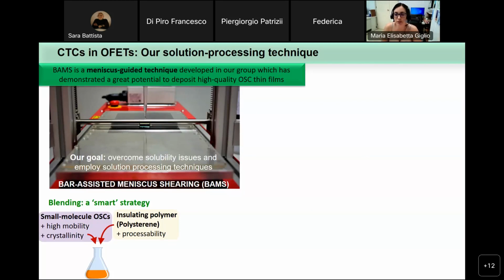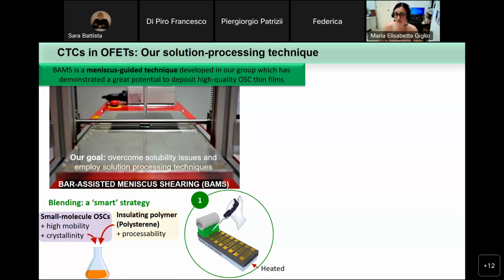So basically we have to prepare the inks, and the addition of the polystyrene as an insulating polymer is key in order to enhance the processability of the materials and to also obtain high mobility and a high crystallinity of the material. So first of all, we position the substrate on this platform, and we inject the ink, so the solutions previously prepared with the materials, in between the substrate and the steel bar.